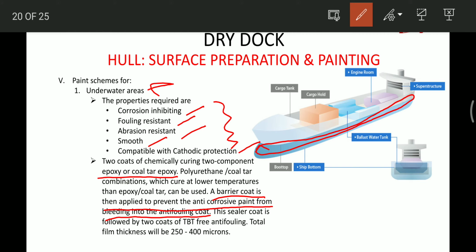First, the anti-corrosive paint, epoxy or coal tar epoxy, or polyurethane or coal tar combination which cures at low temperature, is applied. Then after that, a barrier coat is applied to prevent the anti-corrosive paints from bleeding into the anti-fouling coat. Then the anti-fouling paints are applied. That is, the sealer coat is followed by 2 coats of TBT free anti-fouling paints, and the total film thickness should be about 250 to 400 microns. So this is how we paint the underwater hull area.